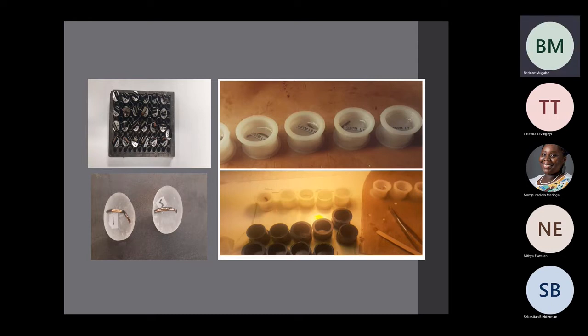So the process that you see there, those white elements that you're seeing on top with name tags inside, that's the curing process. So this was done overnight for 36 hours in order to solidify the samples and create the polished blocks that you see to the bottom left, the small picture with two white polished blocks with the metal immersed in it. So this process of grinding, polishing, it enabled us to understand the composition, the characterization of these samples, because using the scanning electron microscope EDS, we managed to analyze the core of these samples. Next slide, please.